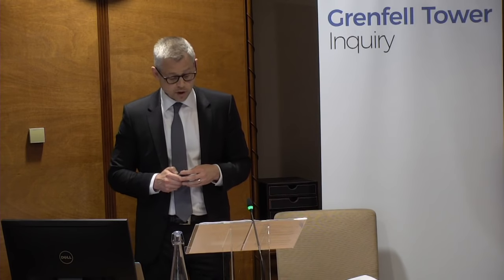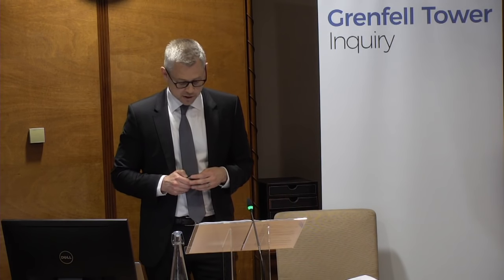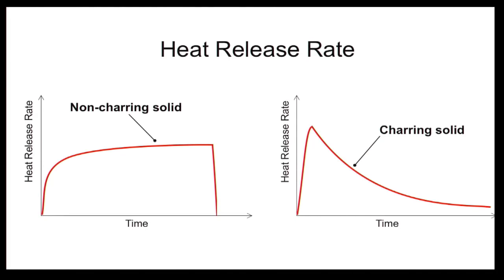At a material level, the heat release rate behavior is dictated to a large extent by the pyrolysis behavior of the solid material. If the material melts, such as in the case of the synthetic polymer material polyethylene, for example, then after ignition, the heat release rate will increase to an essentially steady value until virtually all of the material is consumed. And this is illustrated schematically in the left-hand figure shown here.